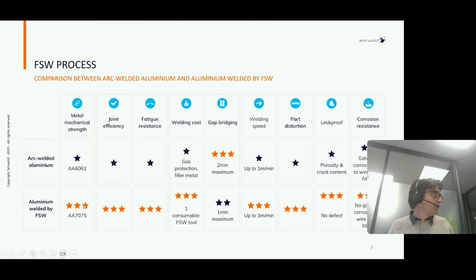Okay, so now for stiffened panels, most of the time today we are using arc welding, can be TIG, generally it's MIG welding, to weld extrusions together to get a stiffened panel. So in this chart, we compare the different properties, arc welding, mainly MIG welding, versus friction stir welding. If we look at the mechanical strength, friction stir welding is better. Why? Because we can weld any kind of aluminum alloy, including the high strength aluminum alloy such as 7075.